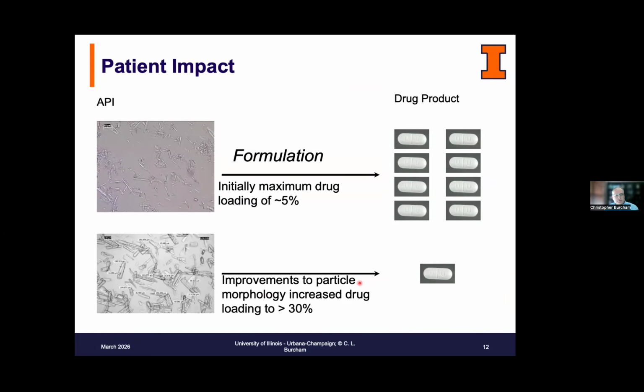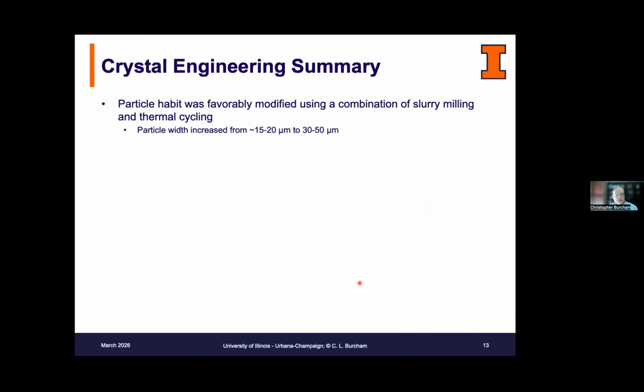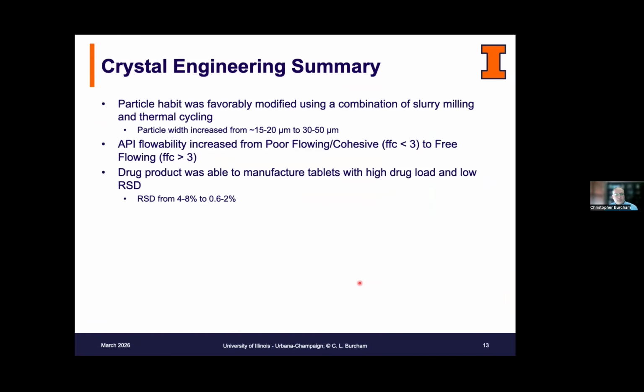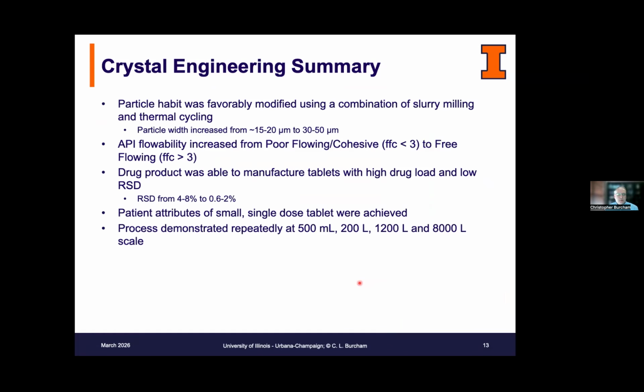But this is an old story. It's one that's been told a number of times. We were able to increase the habit, like I showed. We were able to increase flowability. We're able to greatly reduce the RSD during tableting on the tablet weight. We're able to get a single tablet, and we're able to scale this from 500 milliliters up to 8,000 liters in scale and transfer it to commercial scale. So huge success. Why am I presenting this though?